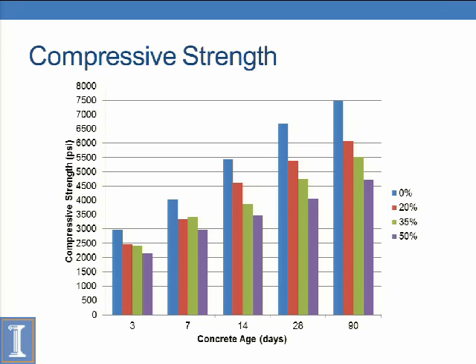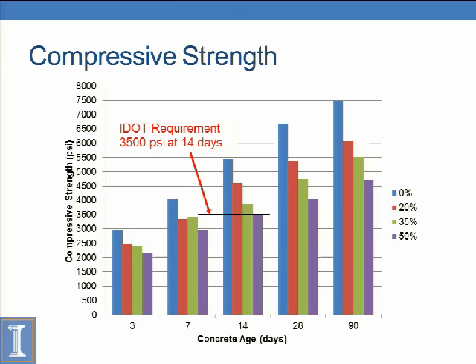0, 20, 35, and 50 going down. And as you can see, at our ages, our strength goes up with age, as expected, but at each age, there's a reduction in strength due to the FRAP content. What's important to note here is the IDOT strength requirement, which requires 3,500 PSI at 14 days. For the most part, these mixes pass. The 50% was just below that limit. It was 0.3% below that limit, but with other mixes we got it above 3,500.